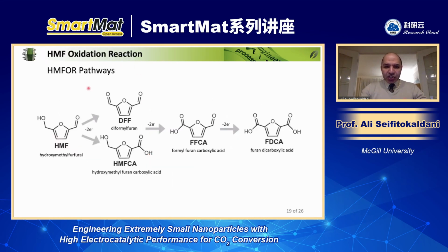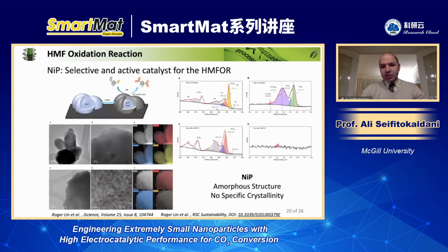So again, just quickly showing you what happens when you start with HMF and you are oxidizing that. You can go all the way through 6 electron transfer steps to form the carboxylic acid, FDCA. But it can go through different pathways. You may produce HMFCA or DFF, but eventually FFCA and then FDCA. So we developed, again, small nanoparticles, but this time we were working with nickel. Nickel is a very good catalyst for most oxidation reactions.